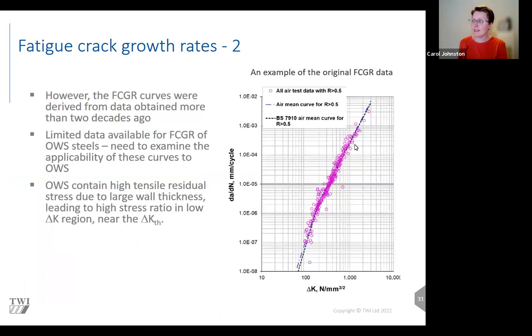An example is the analysis of fatigue crack growth rate data in BS 7910 — they provide two different fatigue crack growth rate curves. One is a simple curve with a single slope, which is quite conservative, particularly at low delta K. When you look at the actual data, the two-slope curve is actually more appropriate, and it's still conservative but slightly less so. There's some work that can be done in the high cycle regime to reduce conservatism while still maintaining some conservatism. The suggestion of looking at different welding consumables and their fatigue behaviour also sounds interesting.